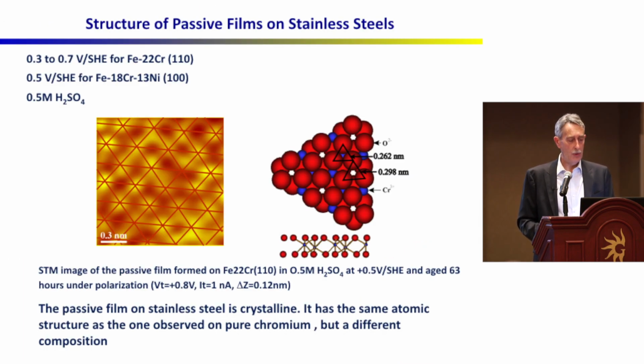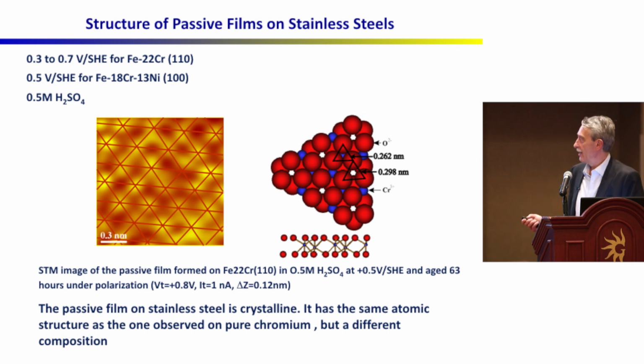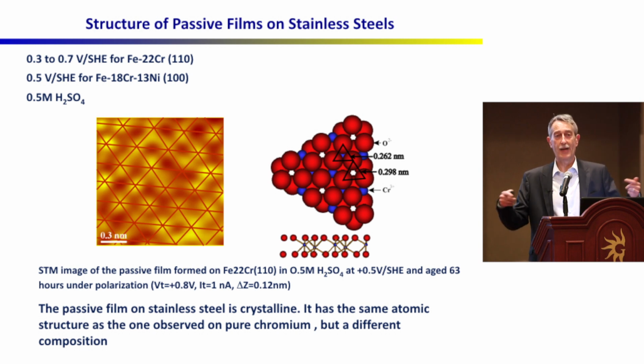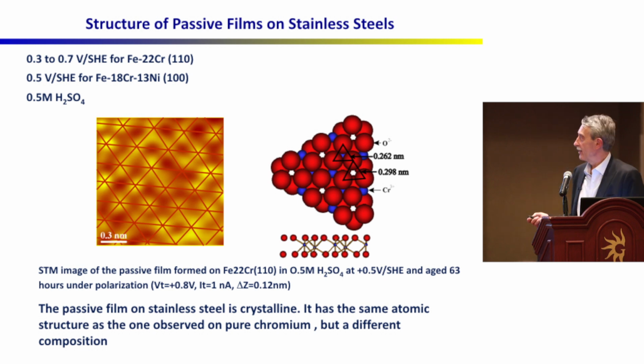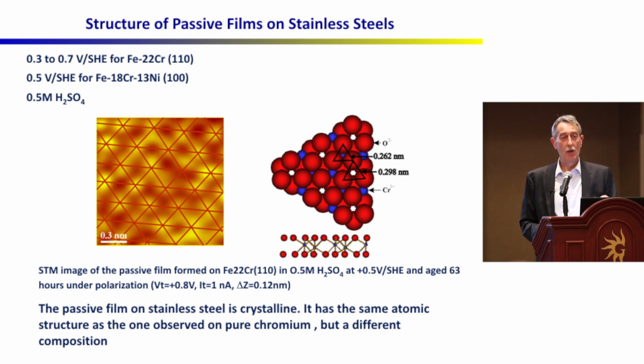We looked at both ferritic and austenitic stainless steels, and this is a typical STM image. So you see, again, the maxima in the tunneling current, and this is the model corresponding to this image. And again, this corresponds actually to the basal plane of chromium oxide. Of course, there is iron in it. We know that, and it was known already from XPS data. So there is iron in this lattice, but this is essentially the lattice of chromium oxide, and it's the basal plane because, again, that's the most stable.